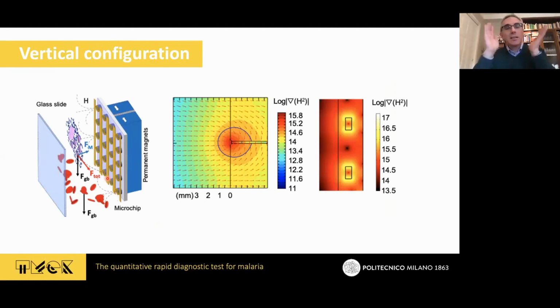Now, what about the real configuration? So far, we have been discussing a horizontal configuration in which, in principle, we were supposed to use a direct competition between magnetic force pointing upwards and gravity pointing downwards. But in practice, we realized that the best configuration is a vertical one. It's a vertical one because for the horizontal configuration, you can easily capture a particle only if the height of the cell is very, very small, around 40, 50 microns. But in order to have a larger volume of blood, we decided to work with a 500 micron height of the well, and we work in the vertical configuration.